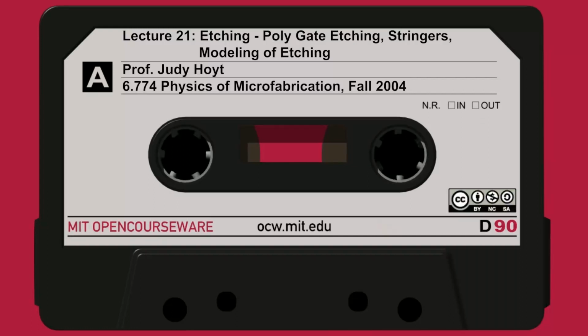And this black region on top is meant to represent the polysilicon. So remember, polysilicon is always deposited everywhere across the chip. So the black region is the thickness of the poly. Now, you notice that on the sloped portion, the thickness of the poly from here to here is given by T poly divided by the cosine theta, right? So that it's thicker here than it is here. It's just by geometry. So the thicker portion of the poly here means that in order to get clear of all the poly and to avoid forming a stringer down here, you need to increase the etch time. And in fact, this formula gives you a calculation of the over etch in percent that you would need for this topography.